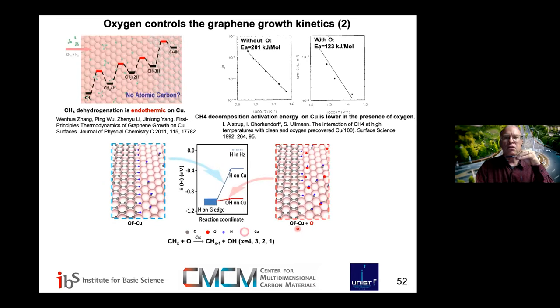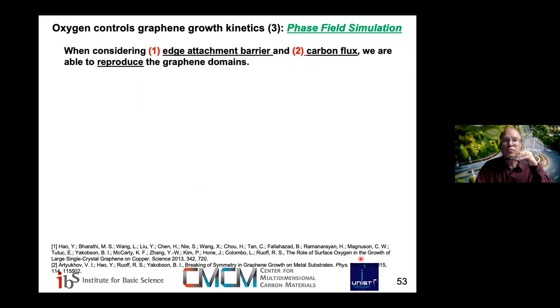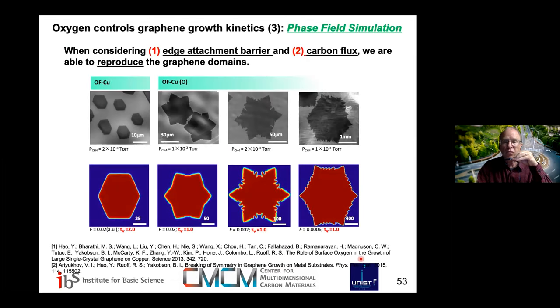These are some of the roles that oxygen can play in terms of blocking nucleation because of passivation of much of the copper foil. Using the C13 labeling, we mapped kinetics and better understood structures appearing with or without oxygen. We actually learned that growth was faster in the presence of oxygen for regions that nucleated and could sustain growth — just that the nucleation rate was much, much lower. The main conclusion from colleagues' modeling was that oxygen helps to reduce the edge attachment barrier. We also collaborated on phase field simulations, which matched well and helped to rationalize the structures we were seeing.